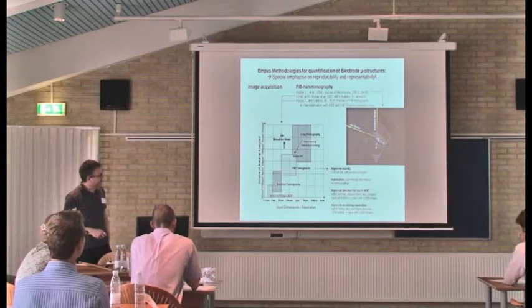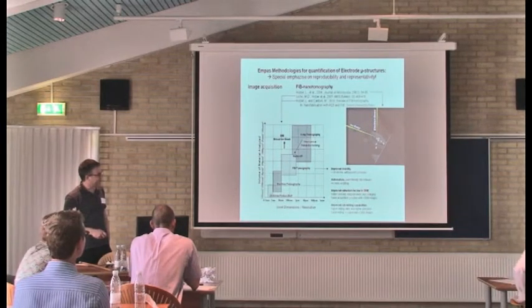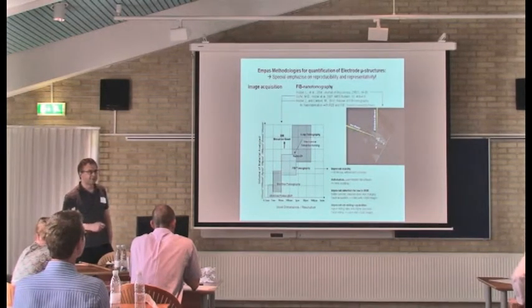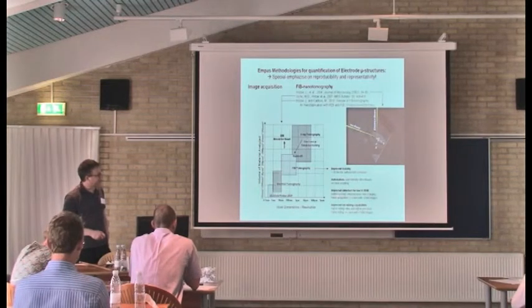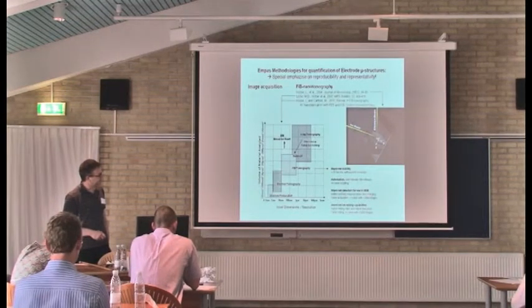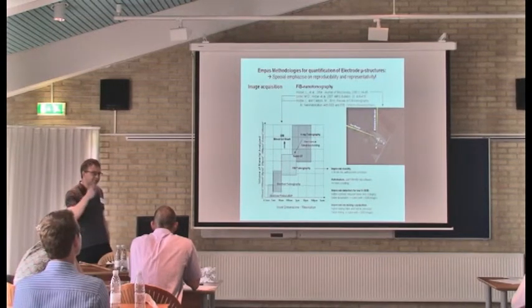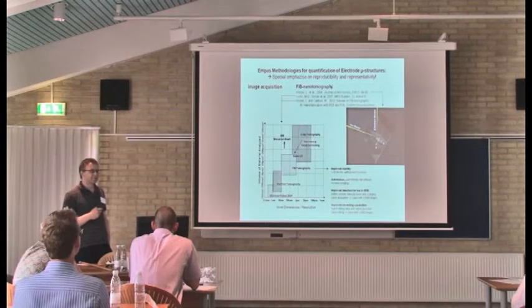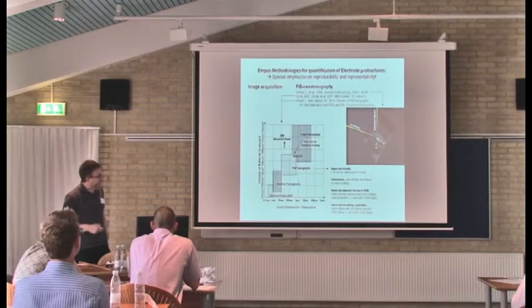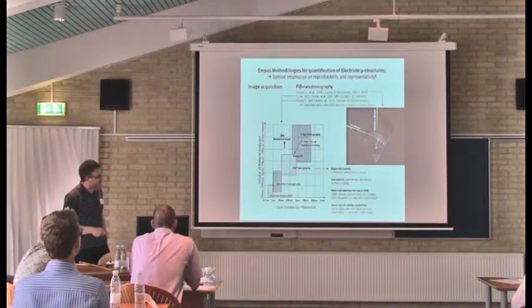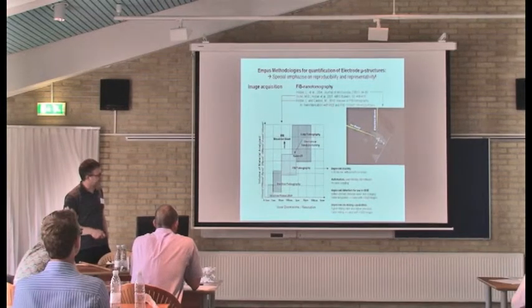Also very much improved is the detection for the low kV backscatter imaging. Contrast is becoming better, less charging, and very important, less noise. That is the possibility to do faster imaging, which is important to go to larger cubes.